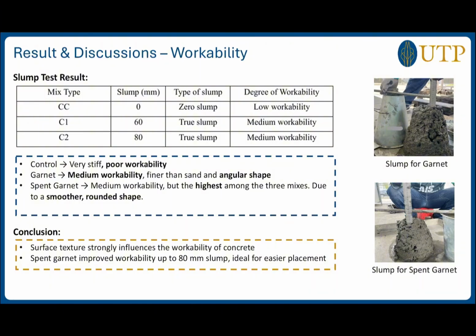Moving on to workability for fresh concrete, and these are the results. Here we can see for control concrete, it records 0 slump, which is showing that low workability. For garnet mix, it increased the slump to 60 millimeter, showing that medium workability. And the spent garnet mix has the highest slump, which is 80 millimeter, and indicates medium workability also. And this is because of the smoother and rounded shape, which can give better flow to the cement. In conclusion, surface texture strongly influence the workability of concrete, where spent garnet improve workability up to 80 mm slump, which is ideal for easier placement.